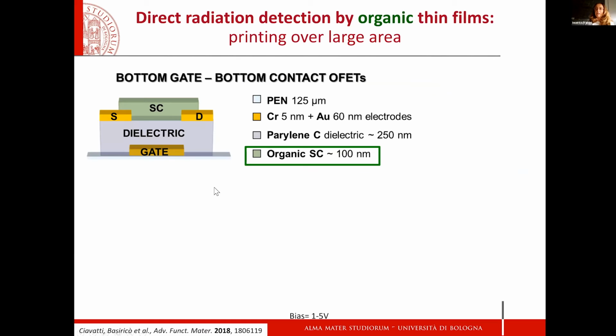Now, let me focus very briefly on how these organic thin film detectors are made. Well, they're basically simple organic thin film transistors fabricated onto flexible substrate in the bottom gate, bottom contact geometry. I'm here reporting one geometry, but it's not the only one. We can also have different geometries, and that would be a very important parameter to play with to improve the performance, but also a two-terminal device sometimes can be used. So that is a typical example, a good and well-performing one, where you see that the organic semiconductor is very thin, really about 100 nanometers thick.